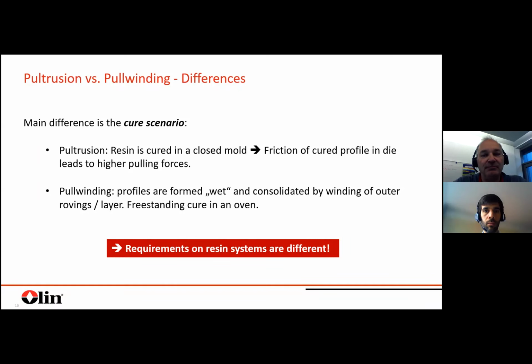In pull winding, you have, I would say, a completely different scenario. You just impregnate it, form it, and then you have a wet, let's call it profile, which is consolidated by winding, and then you pull it through a post-curing oven. So it's a freestanding cure. It's not in contact with any die during the cure. So all the challenges which are related to pultrusion are not given. That means that for these two processes, the requirements on the resins are really different. You can use both of them in the other process, but it will have a negative impact on productivity, quality, or whatever.